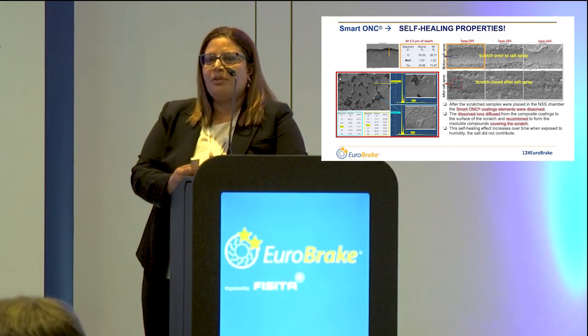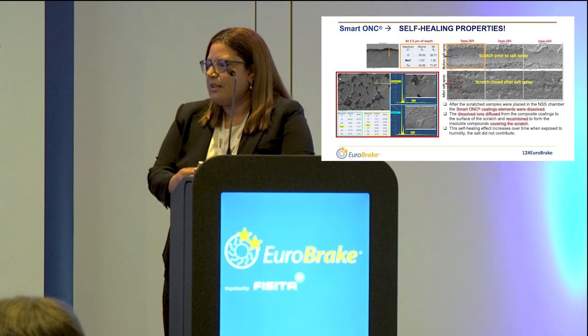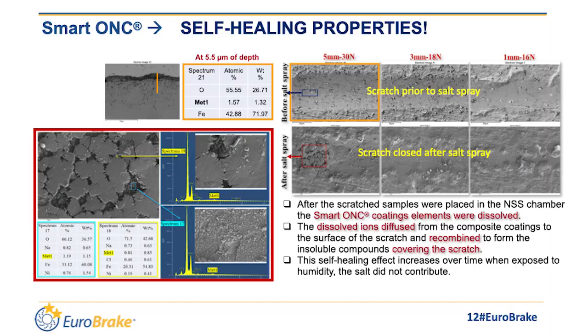So what happened during salt spray? After scratching the sample and putting it under humidity, the Smart ONC coating elements were dissolved, and the dissolved ions diffused from the composite coating to the scratch to recombine and form a non-soluble coating that covered the scratch. This process of self-healing progresses over time.